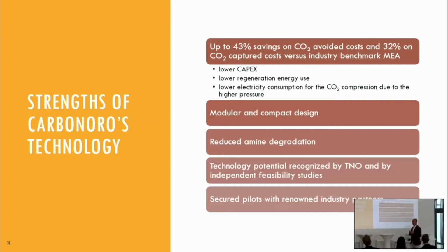Also, modular in design. Installations up to about 100 kiloton capture capacity, for roughly 20% CO2, can be fit on containerized frames that can be built off-site and shipped to the location, so you don't need any building activity or minimal building technology on site. Amine degradation is also reduced. Our solvent is resistant in general to oxidative degradation, and because of the low operating temperature, the thermal degradation is also reduced.